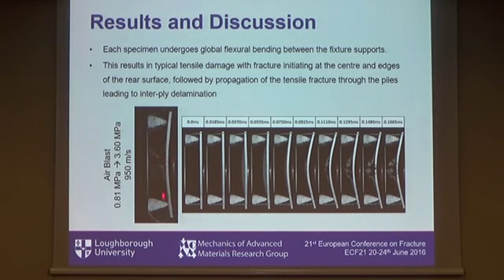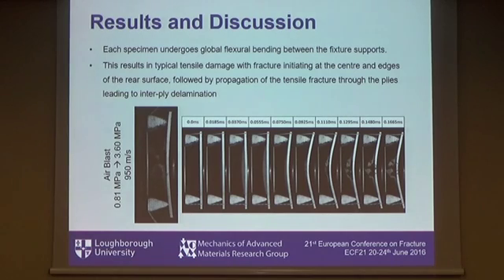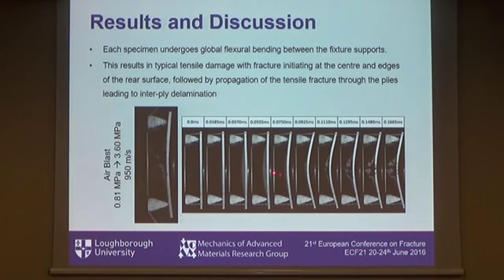As mentioned, this is practically a three-point bending type of loading, and we see quite a lot of damage at the exit site. As we know from simple bending mechanics, the material on the back face is in tensile stress, which leads to a very dangerous type of fiber fracture. This results in a significant loss of the load-bearing capacity of the material. Here are snapshots demonstrating the series of events during the entire time the pressure affects the loaded specimen.